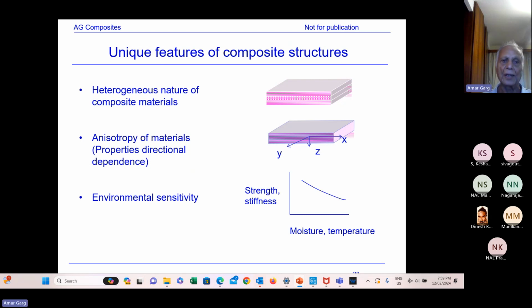Composites are heterogeneous materials which are anisotropic, because anisotropic means they have directional property, whereas metals we always treat as isotropic, that is, in each direction the properties are the same. Although even for metal, in the longitudinal direction, transverse direction, and LT, there is a slight difference in properties like strength because of the grain differences, but not much. We don't differentiate, except when doing the margin analysis, where we would consider the minimum strength in a particular direction, for example when designing a lug and many structures where you have to care whether the direction is L, LT or T. But we still treat that as an isotropic material because the stiffness is the same in all directions.